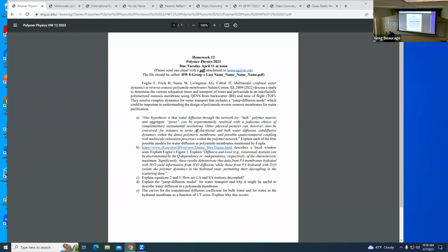So you could separate just by having one component adsorb to the walls. The amide is hydrophilic, so the water sucks up to the walls. When it's on the wall, the transport is going to be much slower than in the bulk. Depending on the pore size, if the pores get to nano size, they can be all wall, because there's a molecular size and then there's what's adsorbed to the surface.